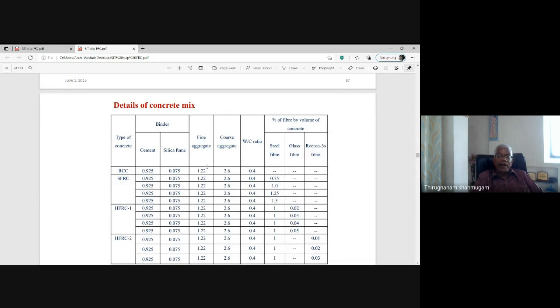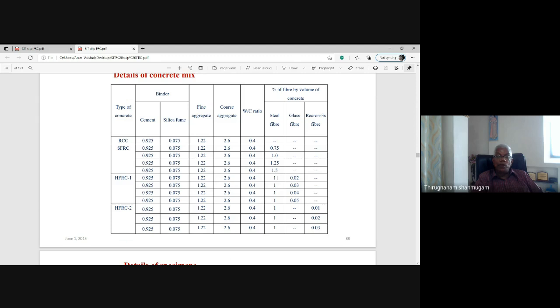This is a sample of the mixed fiber reinforced concrete mix. Conventional concrete with fibers, and steel fiber concrete at 0.75, 1, 1.25, 1.5. That is a variation of volume fraction. For the hybrid fiber reinforced concrete, we take the optimum proportion of 1 for all this. The Recron 3S fibers and glass fibers are used by weight of cement, 0.02, 0.03, etc. Very little quantity, because the density is very, very low, so the number of fibers is huge enough. Here the density is as much as 8 gram per cubic centimeter, so the number of fibers is less. So we are equating these two as a fiber input.